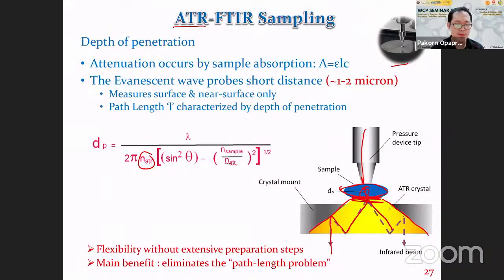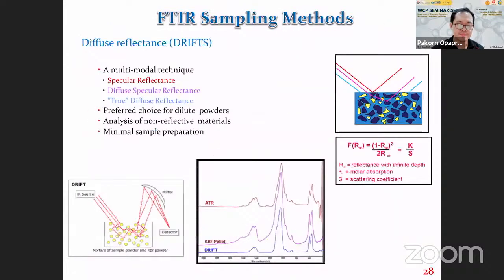Now, the unique character of this technique is that the depth of penetration into the sample depends on many factors. Number one, it depends on the refractive index of the sample and the refractive index of the crystal. Number two, it depends on the frequency or wavelength of the infrared light, and it also depends on the angle of incidence of the beam. So there are three variables we can vary, and this also offers the opportunity to get more important, detailed information from the measurement. I will go to that in detail later on.